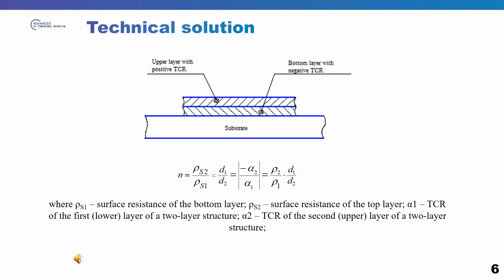By choosing in a certain way the ratio of the thicknesses of layers with positive and negative TCR in a two-layer thin film structure, it is possible to realize self-compensation of the temperature dependence of the resistance of such a thin film solid solution. The resistance ratio in this case is calculated according to the formula shown on the slide. It should also be noted that the temporary drift of resistance for these pairs has opposite directions, which can also theoretically reduce instability.